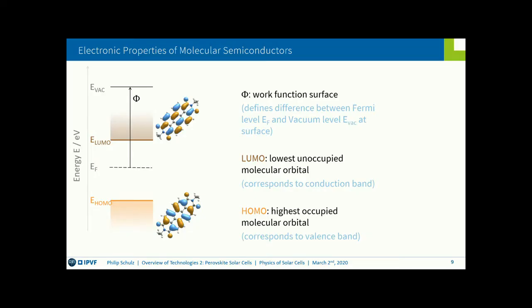And then the LUMO is the lowest unoccupied molecular orbital. It corresponds to the conduction band in your inorganic solid, whereas the HOMO is the highest occupied molecular orbital, which corresponds to your valence band. So why do we make this differentiation? That is because these electronic states are still localized and exhibit very flat bands. So you almost have discrete energetic transitions compared to a band structure that has a high curvature of bands. But nonetheless, make no mistake, they correspond to the conduction band and valence band.